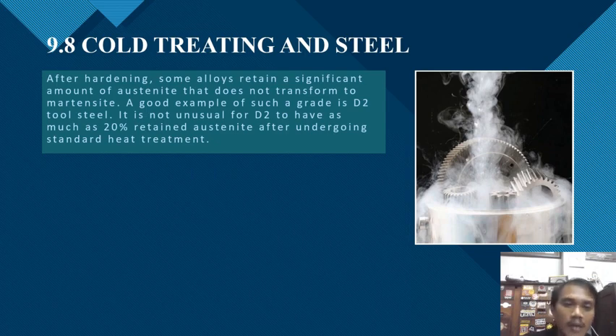After hardening, some alloys retain a significant amount of austenite that does not transform to martensite. A good example of such a grade is D2 tool steel. It is not unusual for D2 to have as much as 20% retained austenite after undergoing standard heat treatment.